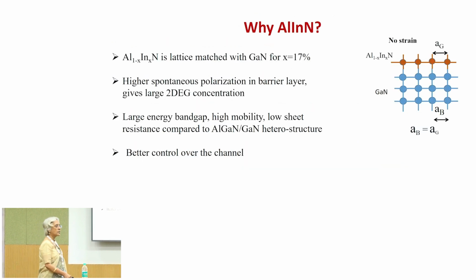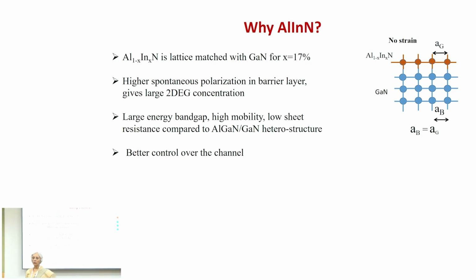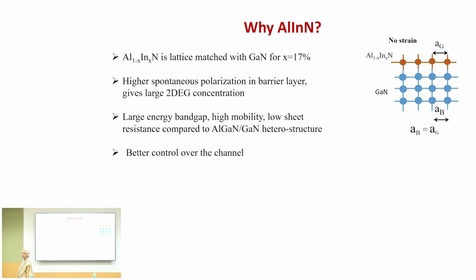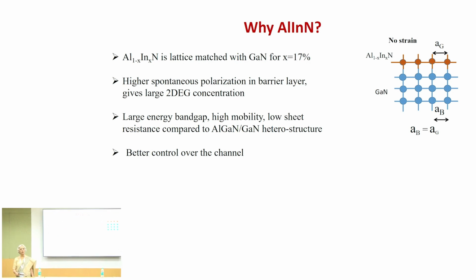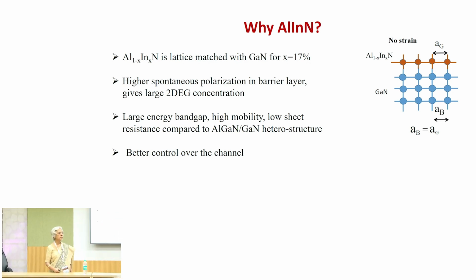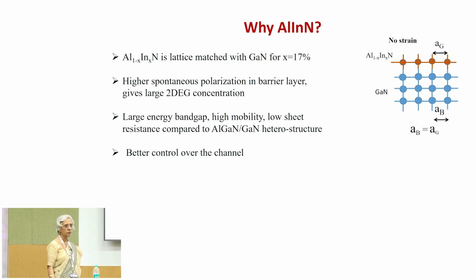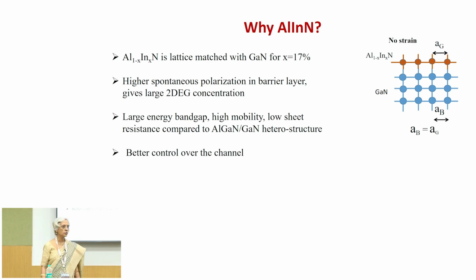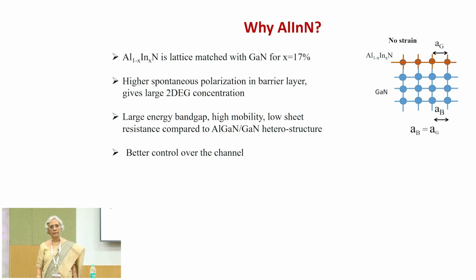So, let me first start with why we focused on aluminum indium nitride. Now, when I say aluminum indium nitride, I mean a particular composition, which has 0.83 mole fraction of aluminum, 0.17 of indium, and nitrogen. This particular composition of aluminum indium nitride is lattice matched to gallium nitride.